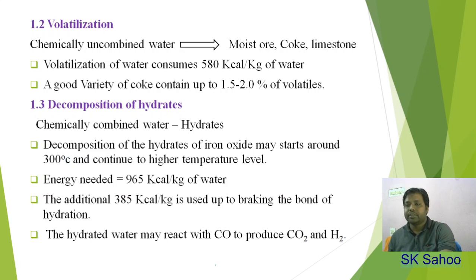The energy needed is about 965 kilocalorie per kg of water, so it is somewhat higher. What is the additional 385 kilocalorie per kg used for? It is used for breaking the bond of hydration. Then after that it is evaporated, that means gasified.